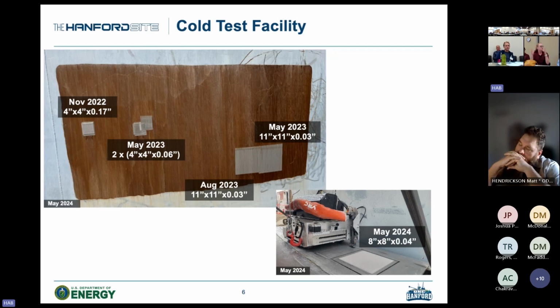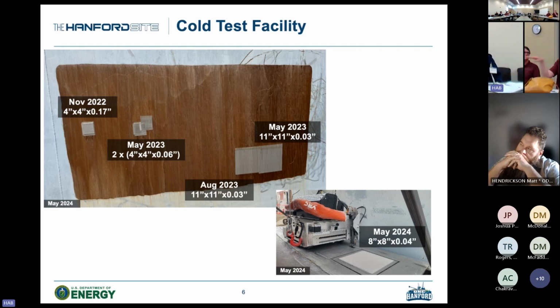And then the larger patches were just to show the maximum widths that we can achieve with these systems. So the cold spray wall crawler has a maximum raster width of 11 inches. And then that can be an unlimited length, because you have the cold spray system rastering across a maximum width, and it's just going to step down and then it comes back up to build up those layers. So it goes down and back over. So the floor crawler, its maximum rastering width is 8 inches wide. So that's what that system has.